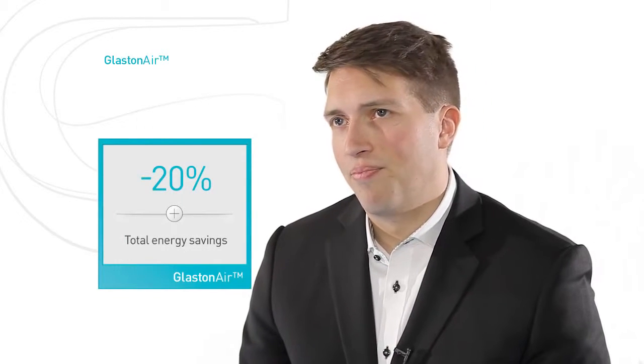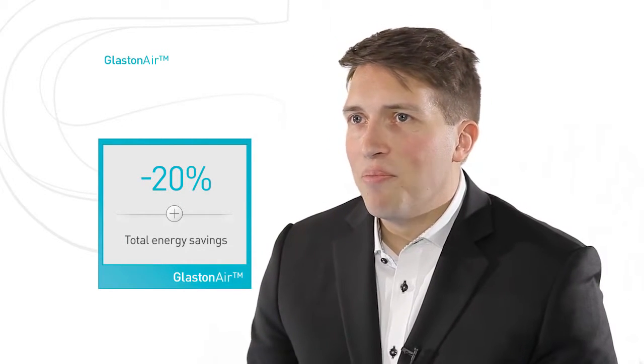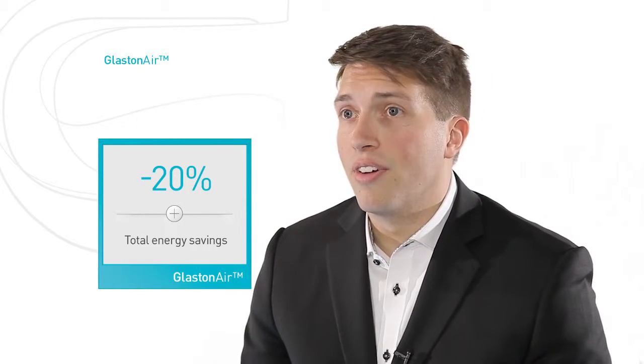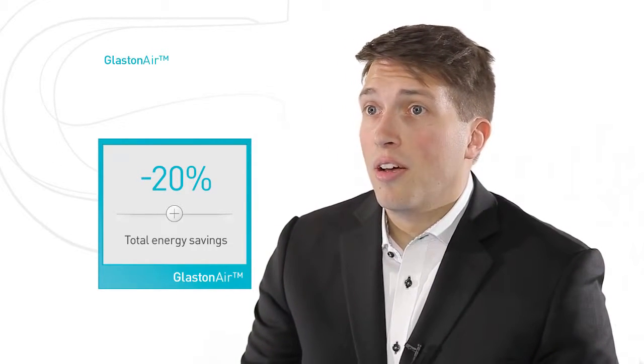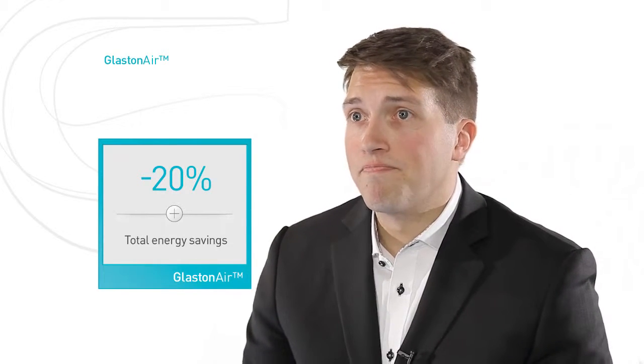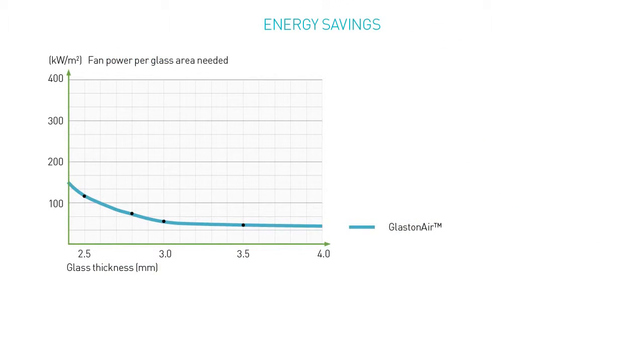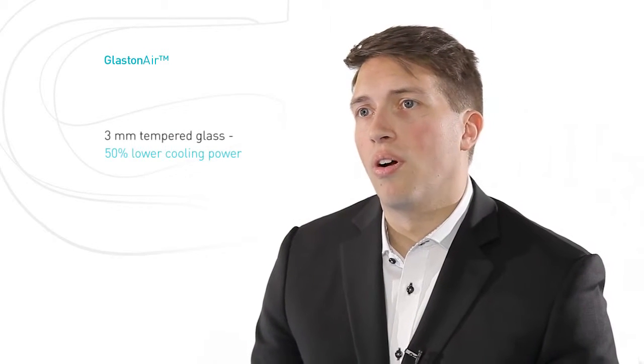And the best part is, with GlastonAir, the thinner the glass, the more energy is saved. It is actually the same exponentially growing phenomenon of energy need as I just mentioned, but in the opposite sense totally. Since the glass can be heated to a higher temperature than in the traditional tempering process, the energy need in the quenching phase is significantly lower. With 3 mm tempered glass, for example, a conventional roller type furnace requires twice the cooling power than GlastonAir.